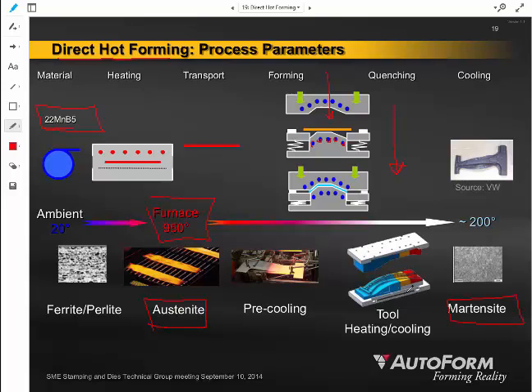Some of the things that we're doing with these hot forming and hot stamping dies is that you can take the die and you can actually, in this illustration you'll see that I have one area that is shaded blue and I have another area shaded red. And what you can do is you can have maybe one area of the tool being held at 400, 450 degrees Celsius, and the other tool being held at 80 degrees Celsius. When you take the big superheated blank and you close it inside of a die that has these two different heating zones, what you're going to end up with is a different rate of cooling in the top half of that panel compared to the bottom half of that panel. And by changing the quenching characteristics, we get different material characteristics as we form this panel.